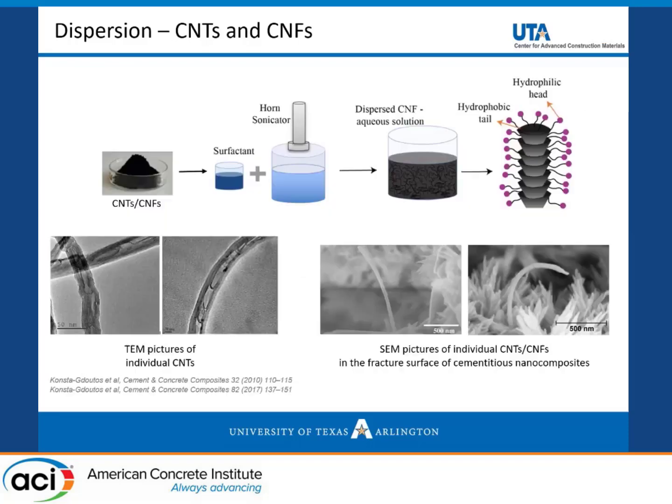So many years ago we developed a technique which is now actually used quite a bit. You start with, for example, carbon nanotube, and then you use ultrasonication and superplasticizer. You need both to have a stable, well-dispersed carbon nanotube. When you use superplasticizer, you have this functionalization, so the material becomes very well dispersed. And I have shown dispersed carbon nanotube.